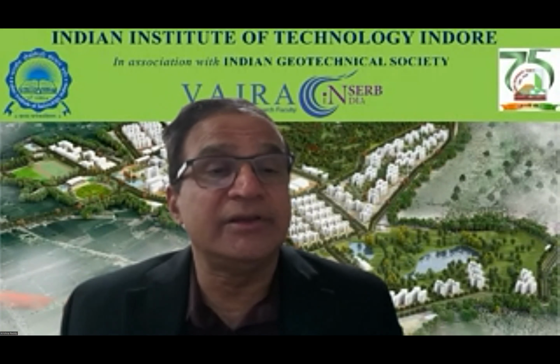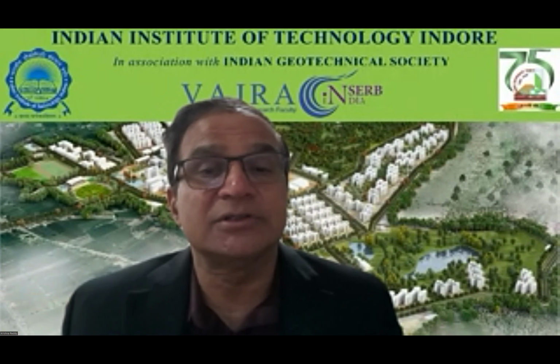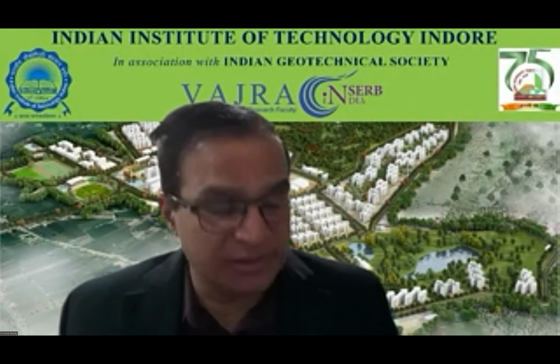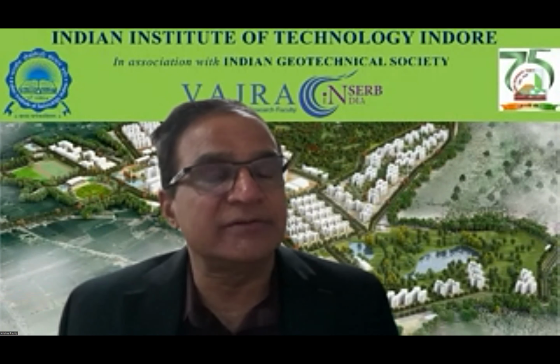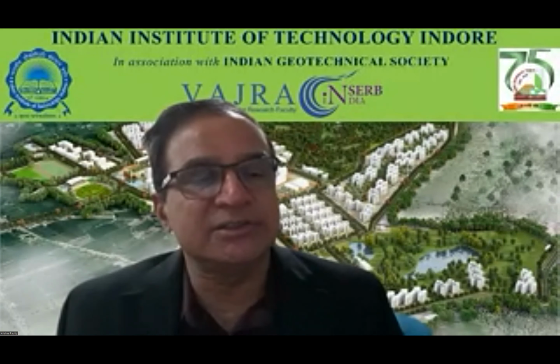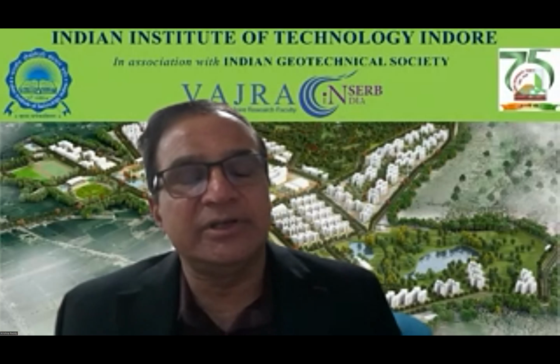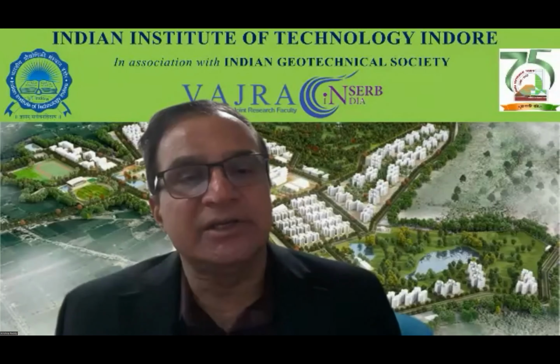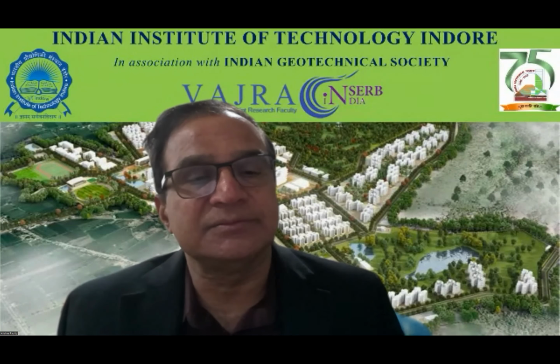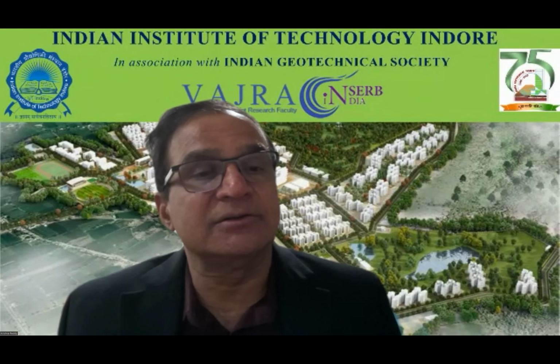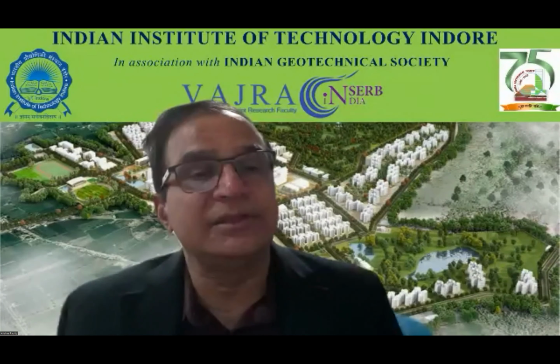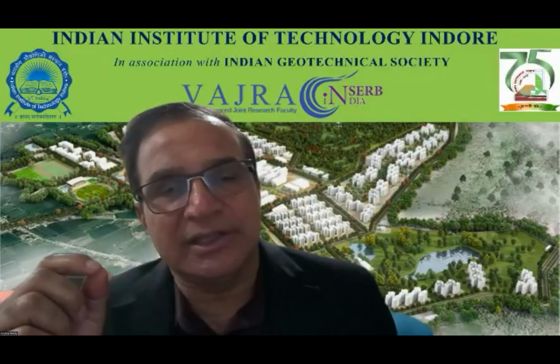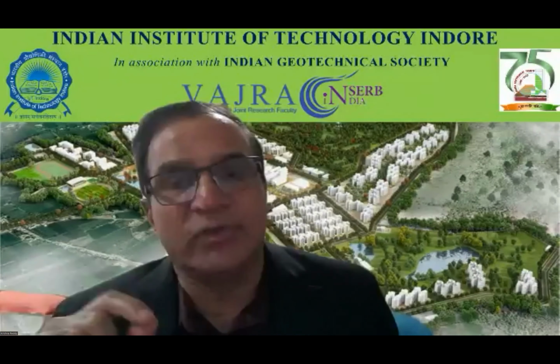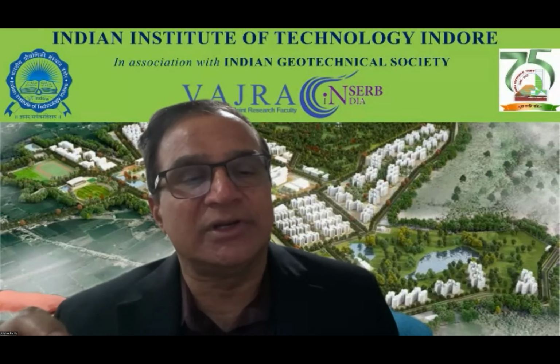Will there be any effect on the fertility of the soil and plant growth after the application of the nanoparticles in the soil? I haven't shown you those results, but we also evaluated the toxicity of nano iron particles on plant growth. We amended the soils with different amounts of nano iron, tried to plant in the soils, and found that there's not much effect. As I said, these nanoparticles are not going to remain toxic forever. When air enters, they get oxidized. The elemental form of nano iron is not stable, so it wants to convert into oxide. Once it becomes oxide, it will not have any effect.